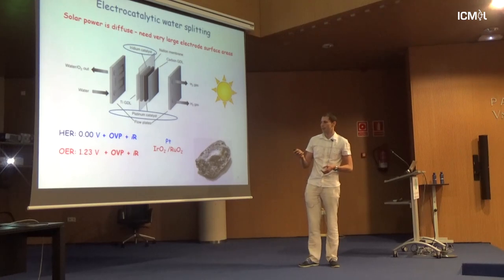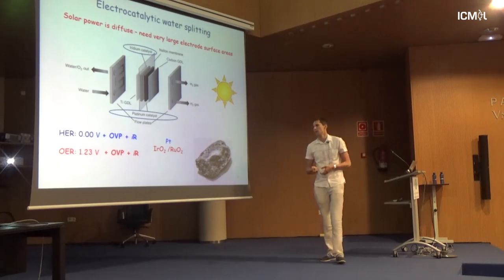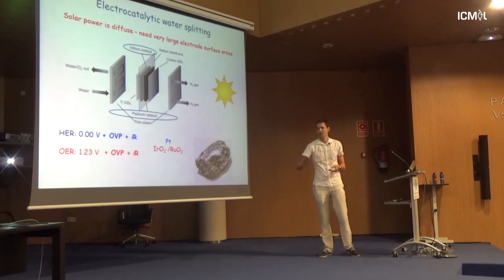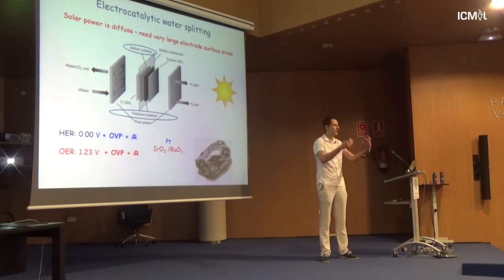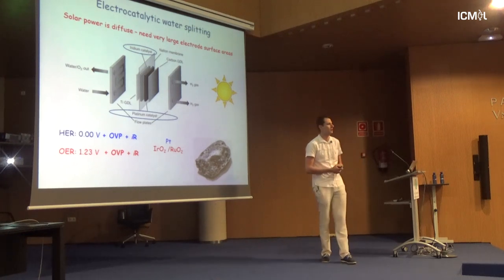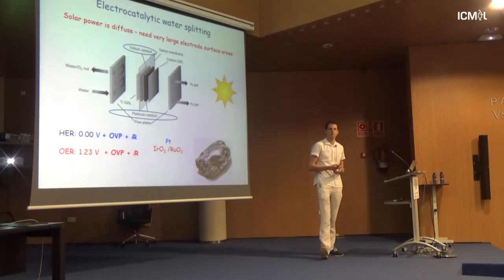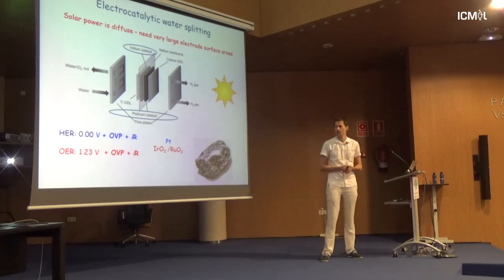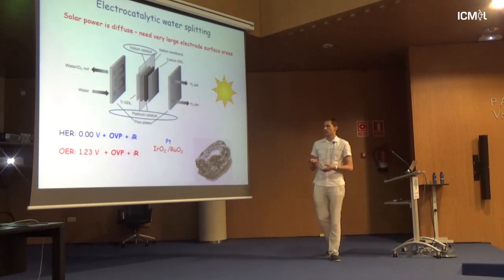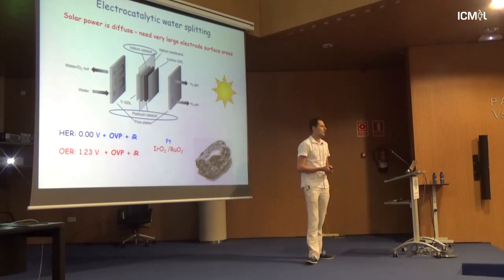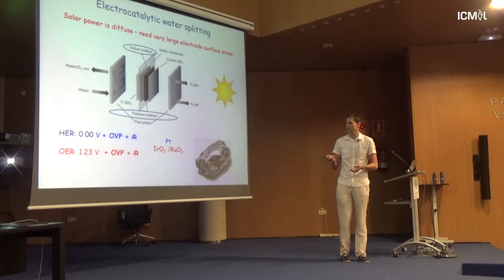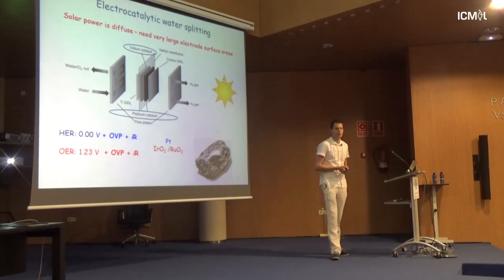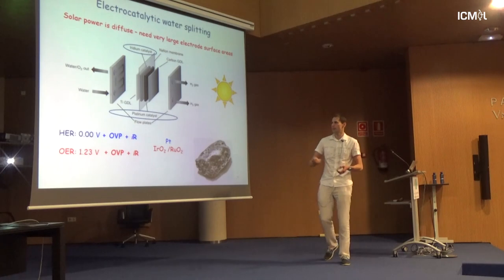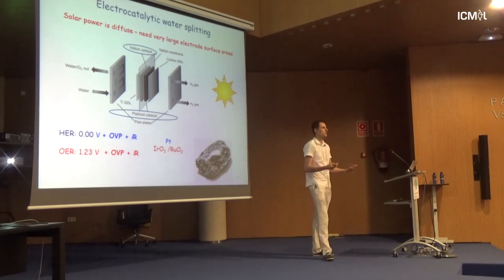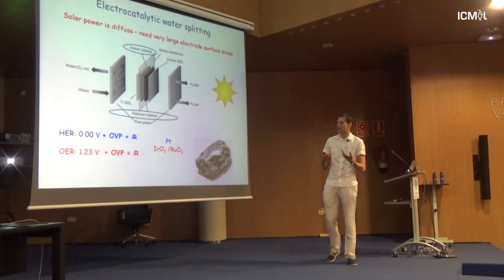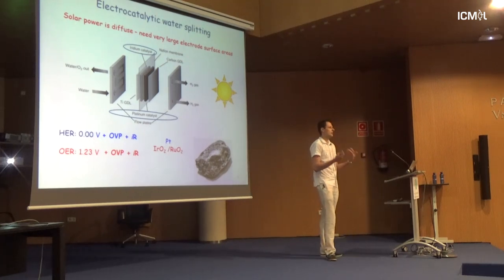And this is reflected in this value, which is called overpotential, or eta. It's an extra potential you need to give in order to drive your hydrogen evolution reaction. So the goal is to minimize this value as much as possible. If you bring it to zero, you can produce hydrogen very nicely. Plus you have this IR, so this is resistance. So again, this gives you an extra message in the design of your catalyst. You want something which is conductive.